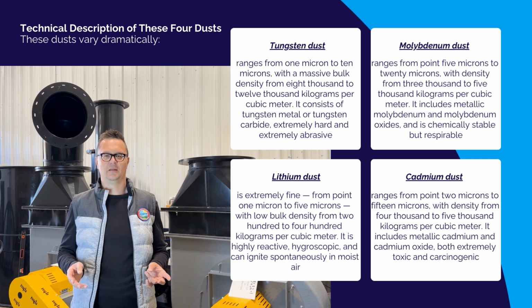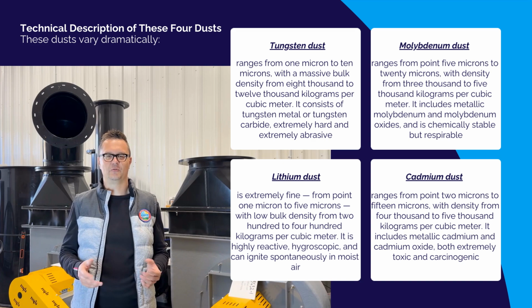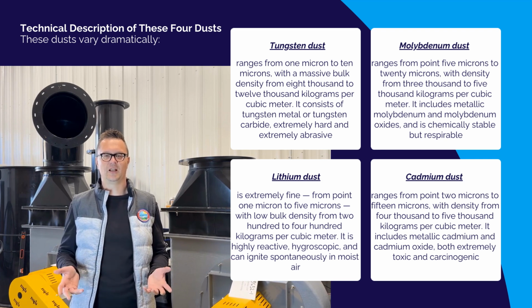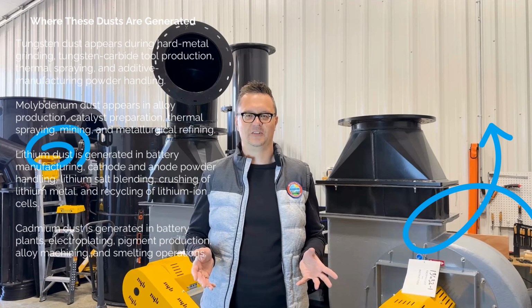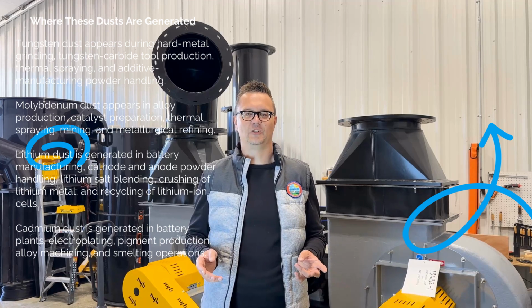Fourth, cadmium dust ranges from 0.2 microns to 15 microns with density from 4,000 to 5,000 kilograms per cubic meter. It includes metallic cadmium and cadmium oxide, both extremely toxic and carcinogenic. This group includes heavy dusts, reactive dusts, toxic dusts, and pyrophoric dusts, all in one dangerous family. Where these dusts are generated, each dust originates from very different industrial processes.